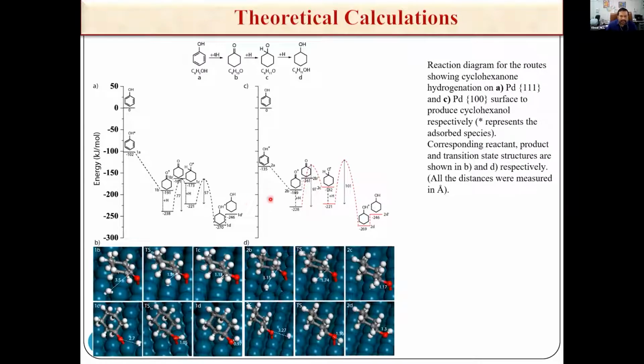Right, so we have done some theoretical calculations, and what it tells us is basically on a 100 surface, which is given here, there is a high barrier for the further hydrogenation of cyclohexanone compared to the 111 case, where the barrier is only 57 kilojoule per mole, so that it can further hydrogenate to make cyclohexanol. Whereas in this case, that doesn't happen.